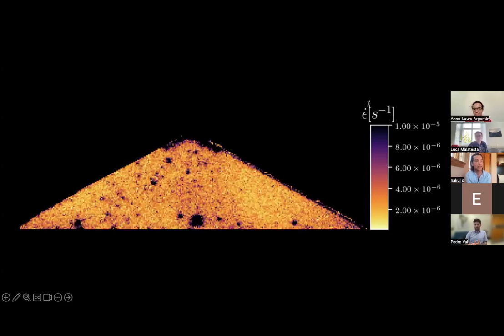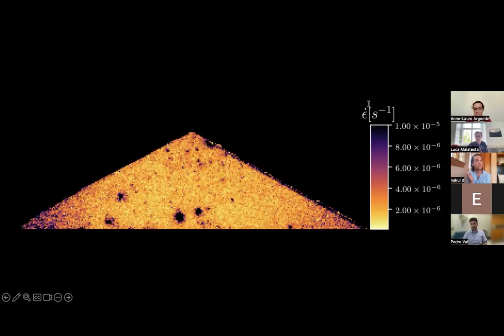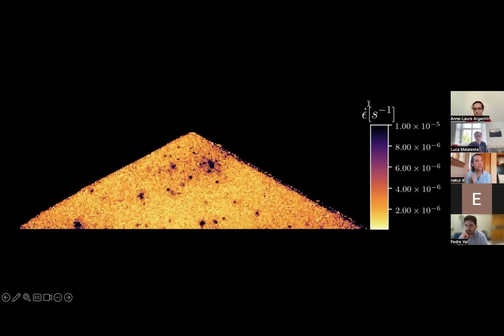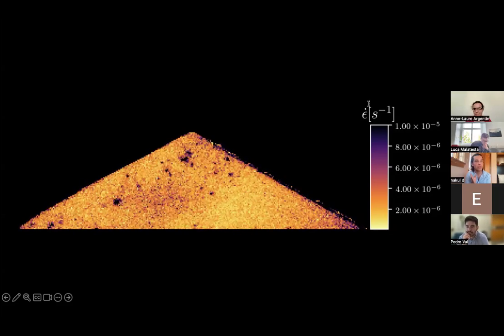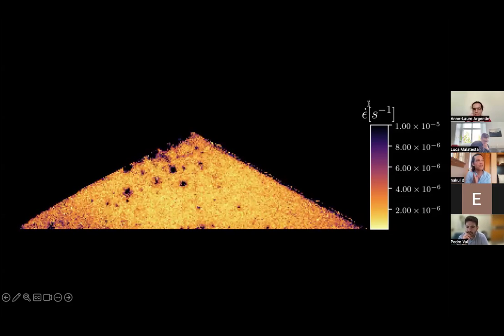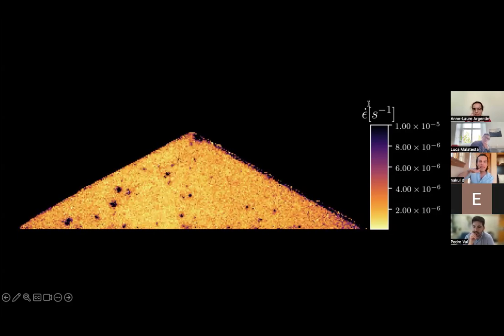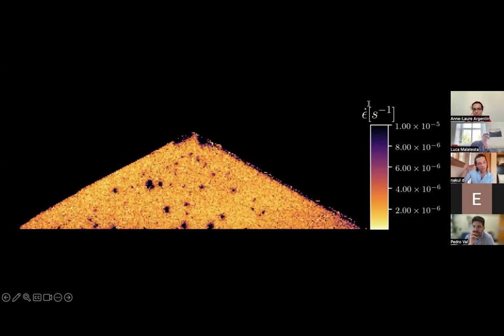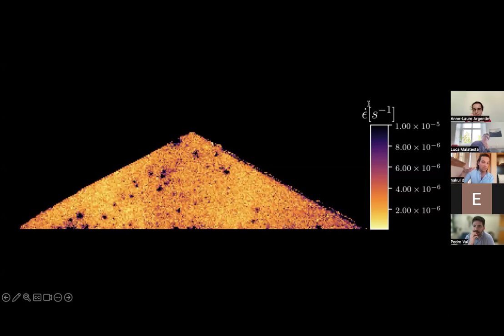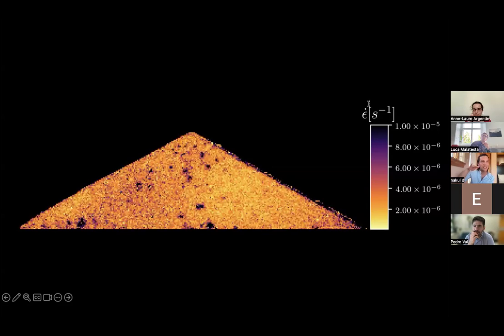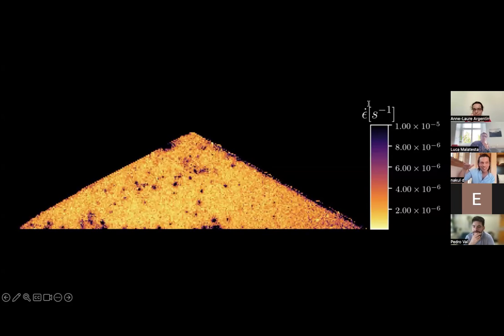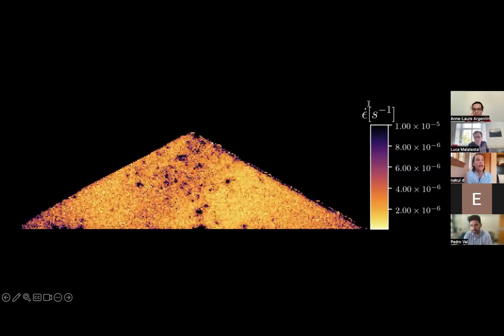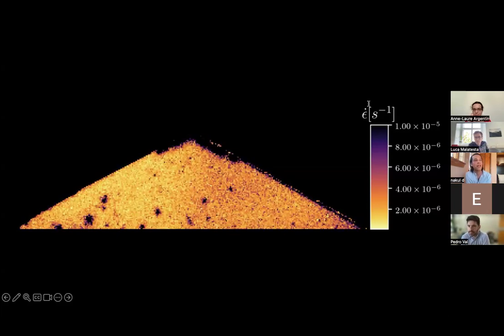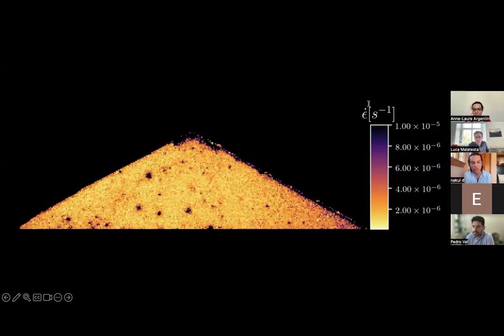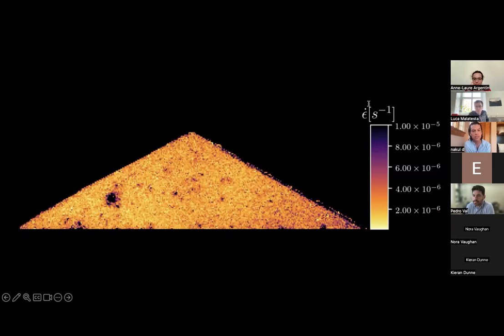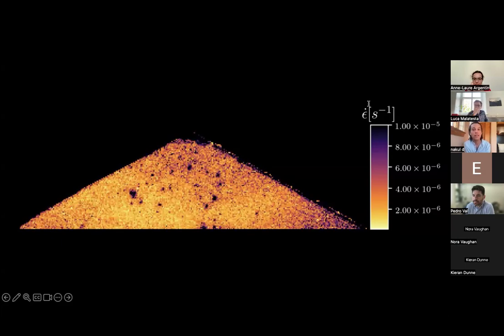Yeah, and I think that under the tapping, the system is compacting. But if you increase the frequency and use sinusoidal driving or white noise driving, my observation is that the pile maintains an agitated state that doesn't relax. But there's a sweet spot of the type of forcing and whether you get aging and relaxation, or whether you get something that is at a roughly elevated and fresh creep rate, let's say. But I don't have really good answers for what range of displacements or voltages, right? The voltage is generating a displacement in the sensor. What that range is, I don't have a good answer to that question.